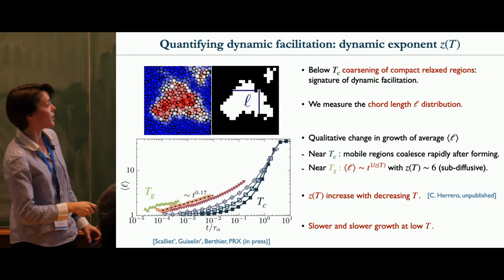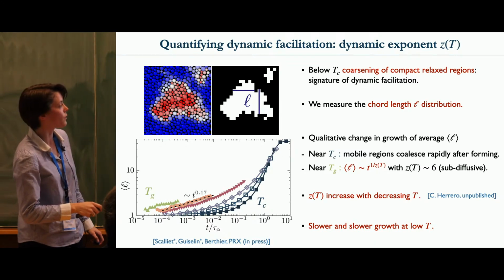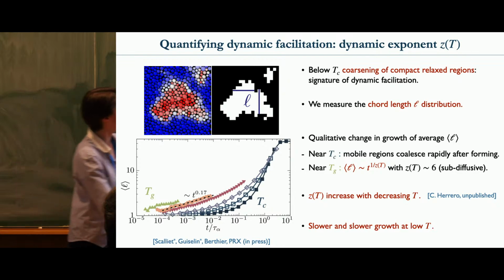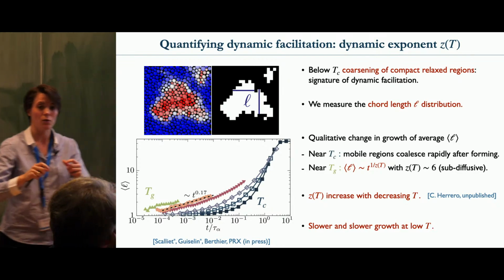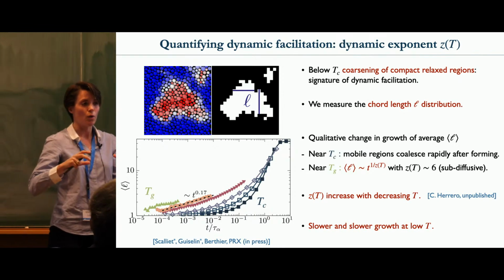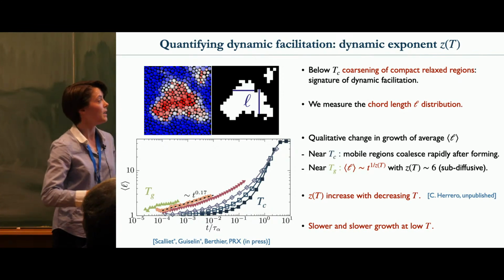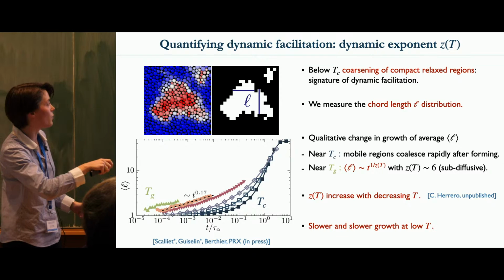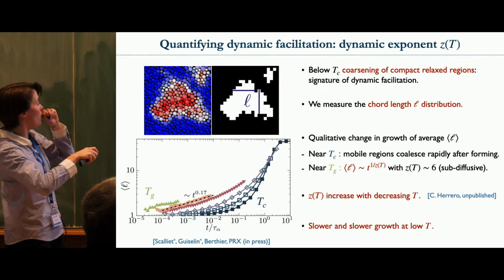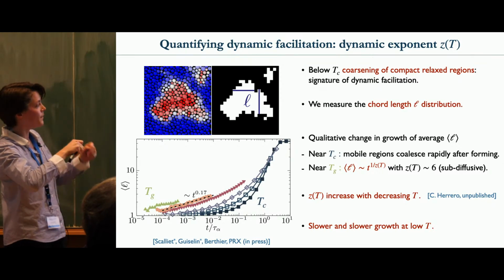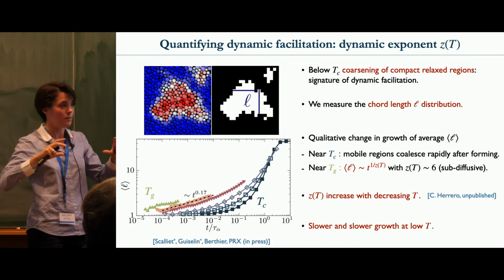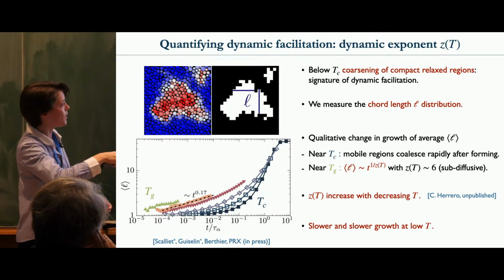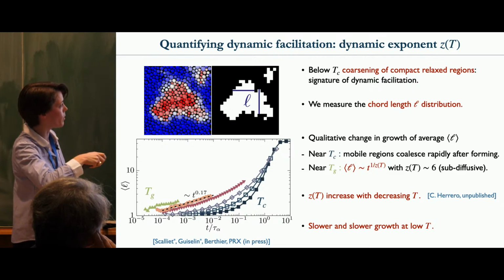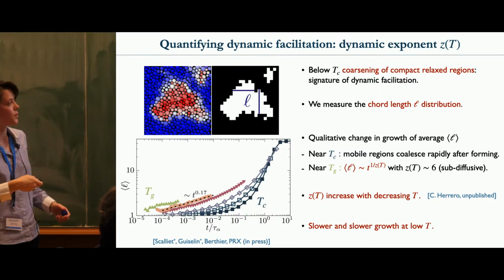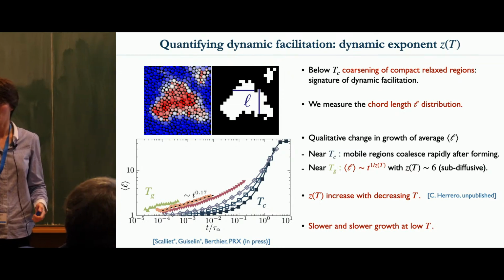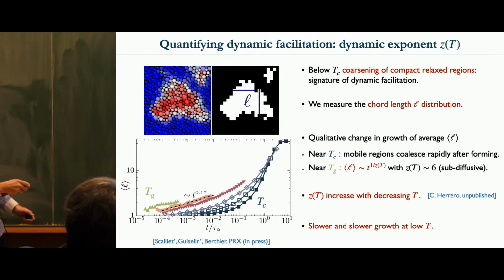What you have is really a qualitative change in the growth of the average cluster length between the mode coupling crossover and TG. At high temperature, the clusters don't really have time to form and grow. They directly merge because there are so many clusters. While at lower temperature, what you have are these very well-defined regions that have time to grow and increase in time. And we can actually fit their growth by a power law. So this is a way to directly quantify and characterize this slow growth of the domains.